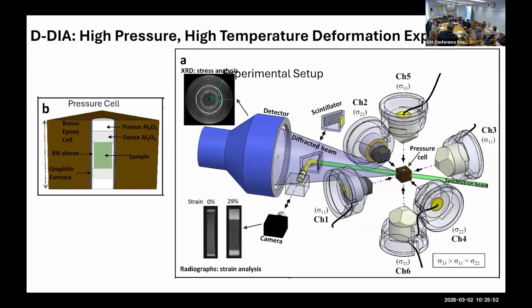And this is just a picture of the setup. So here are these anvils, which are going to go in there, which I'll show you how. You have a pressure cell at the center. And if you cut away the pressure cell, you have these little components, and then you have your sample at the center. The samples are on the order of maybe 1 to 3 millimeters. You can go bigger than that in some applications, but 1 to 3 millimeters is so large that they refer to this as a large volume press, even though it's kind of small.